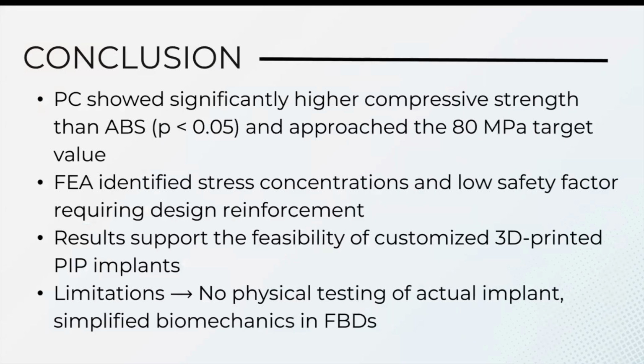In conclusion, from our testing, we found that PC outperformed ABS, showing significantly higher compressive strength and coming very close to our target requirement. Our FEA also highlighted areas of high stress and low safety factor, showing us where the design still needs to be improved.